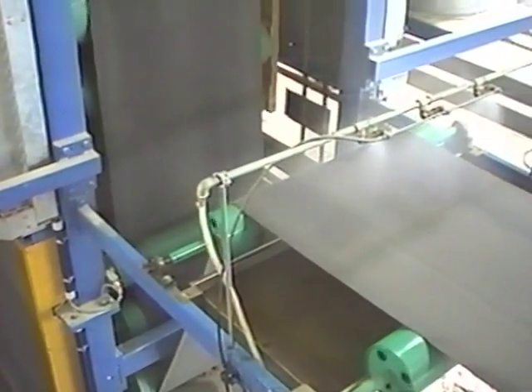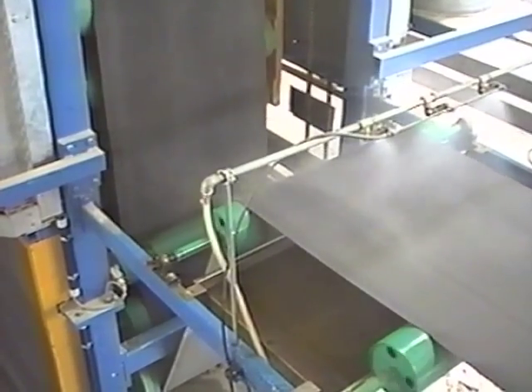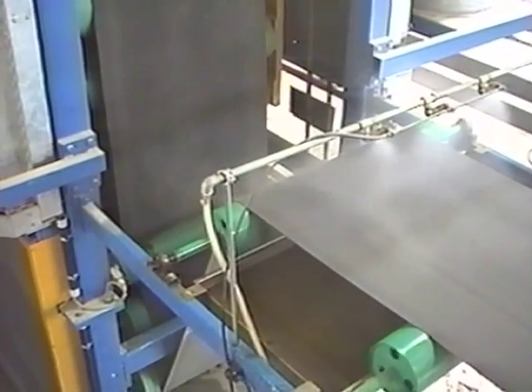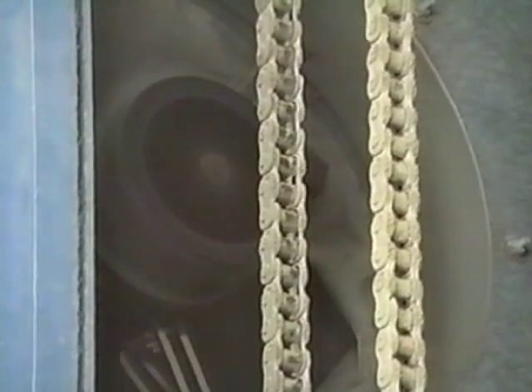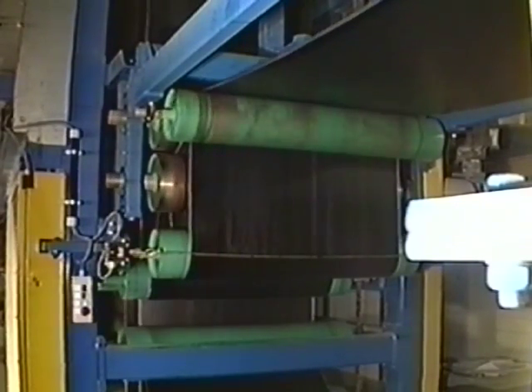After leaving the coating section, the surface of the finished product, which is already cooled to about 40 to 50 degrees centigrade, is sprayed with a thin film of water. Using the heat of evaporation, further optimum cooling to room temperature takes place in the downstream air-cooled unit, which draws in outside air by ventilators and then discharges it again. An additional edge control unit controls the exact flow of the product.